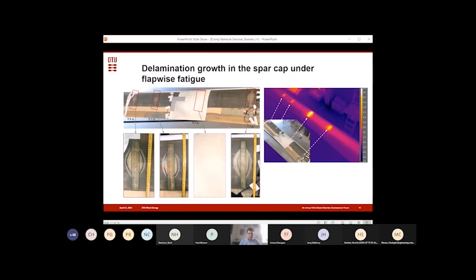And this picture shows these 4 delaminations. The green here shows how they were originally, and then they start growing, and we have marked at different times how much it has grown. And one of them is painted. There's a white paint with a speckle pattern because we use a measuring system called digital image correlation. And it also shows that for one of the delaminations, you cannot see what's happening. The others, where there is no paint, you can easily see what's happening. And of course, the painted one is more representative of a real turbine blade.